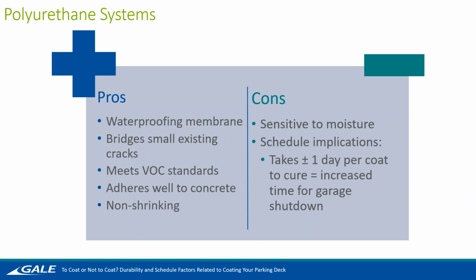So the pros and cons. The pros: it's a waterproofing membrane. It can bridge small existing cracks. So a crack up to 1/16 of an inch, you don't have to repair, and you can just coat right over it. It meets the VOC standards, so it doesn't smell as much. It adheres well to concrete, and it's non-shrinking.